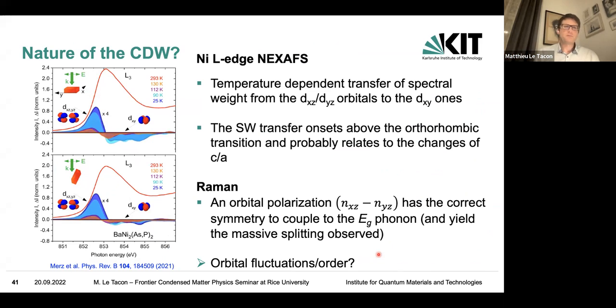So, a final comment maybe about the nature. In the paper of Michael Merz, there was diffraction and thermodynamic measurements, but they also carried out X-ray absorption at the nickel L edge. And one interesting finding is that when they cool the system down across the triclinic phase, they see a very strong transfer of the spectral weight from the t2g orbitals with the out-of-plane character, the dxz or dyz orbitals, to the one which has the in-plane character, the dxy, but that this spectral weight transfer is actually already present in the high temperature phase.